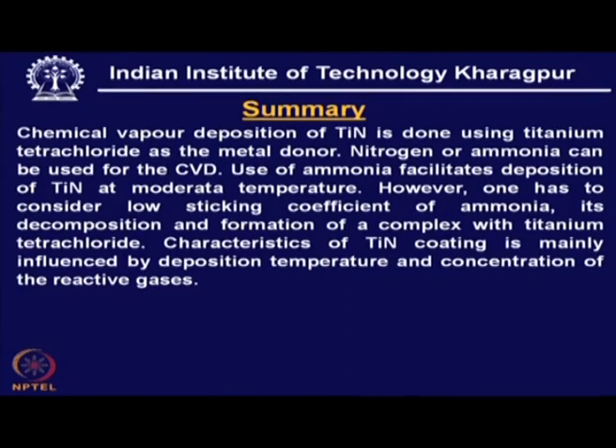So, with this we can summarize the thing. That means chemical vapor deposition of titanium nitride can be done using titanium tetrachloride as the source material, and this is actually the donor of titanium. And as a source for nitrogen we have two options, either nitrogen or ammonia. Nitrogen with hydrogen as the carrier gas can be rather conveniently used, and this particular reaction requires at least a temperature above 800 or 850 degrees to happen, and this reaction can be quite useful for those substrates which are unaffected, say for example cemented tungsten carbide, which can be one of the best candidates for such a thing.